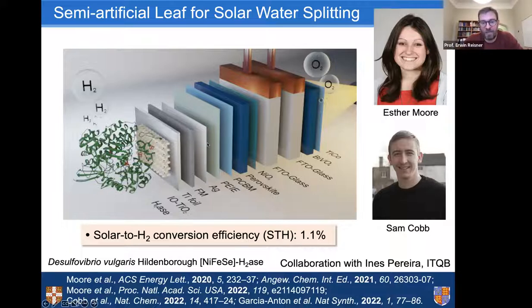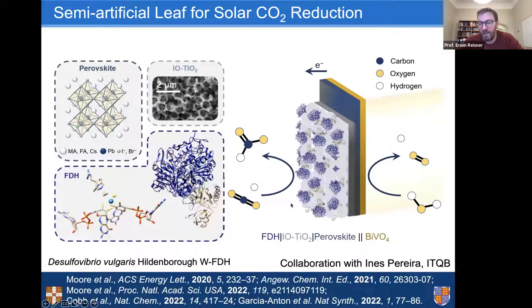So the stack here is the same, except the fuel producing part. And what we have done is we have replaced the carbon nanotubes by a porous metal oxide scaffold that we have to develop to integrate these catalysts. And indeed, when we use these hydrogenases, in this case a nickel iron selenium hydrogenase, we can readily reach an efficiency of 1.1%. We can replace this hydrogenase by carbon dioxide reducing enzymes. In this case, it's a formate dehydrogenase. Also here, I don't want to spend too much time, but in the same stack, just replacing the hydrogenase by formate dehydrogenase, we can now convert carbon dioxide into formate.